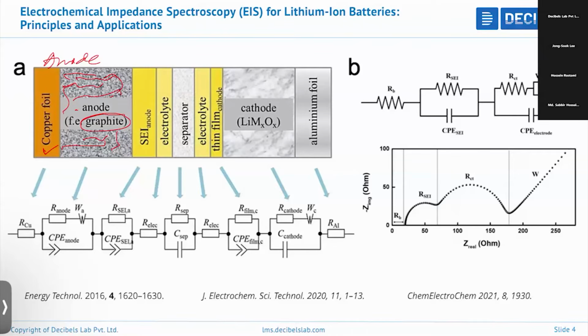After fabricating the battery, during the formation cycle, that is the conditioning cycle, a very thin film forms on the surface of the graphite called the SEI, the solid electrolyte interphase. It's made up of lithium oxides, lithium carbonates, and is a very porous film. I have discussed the SEI's importance in detail in some of the videos in that course.